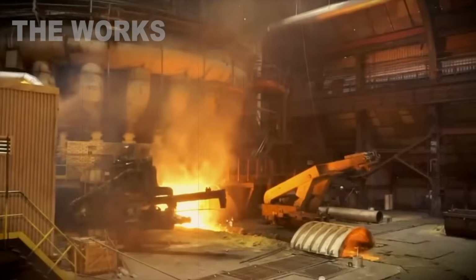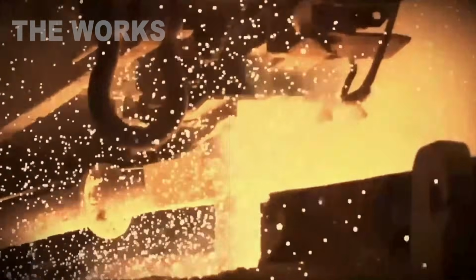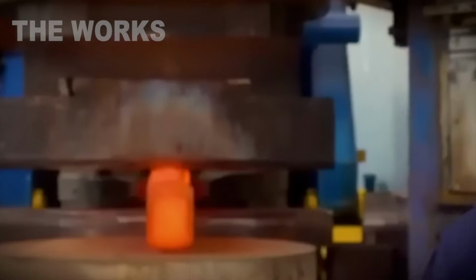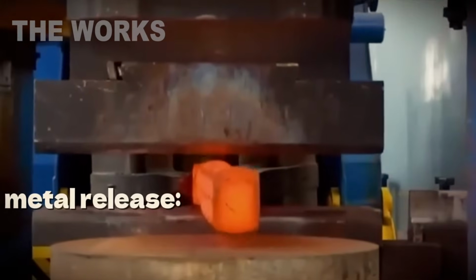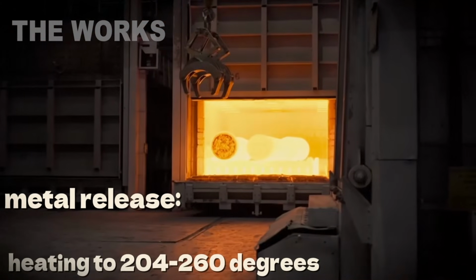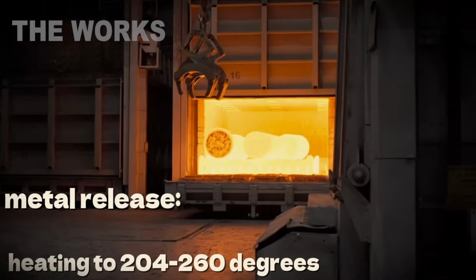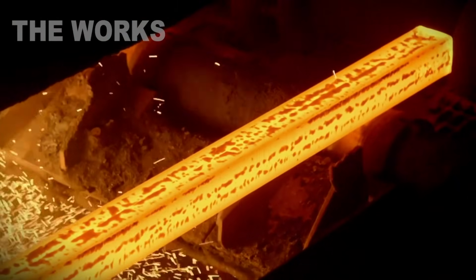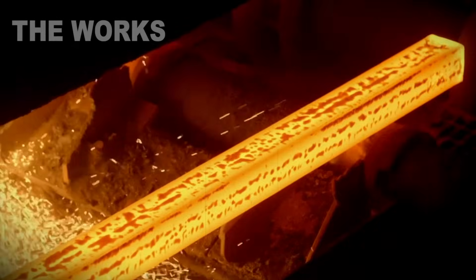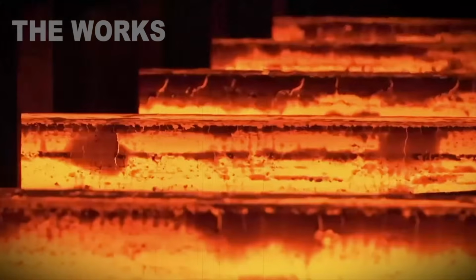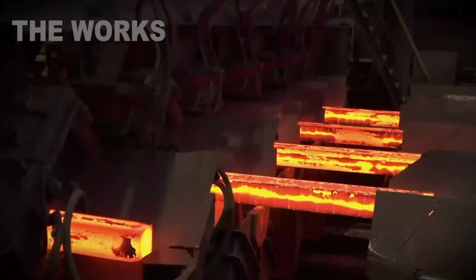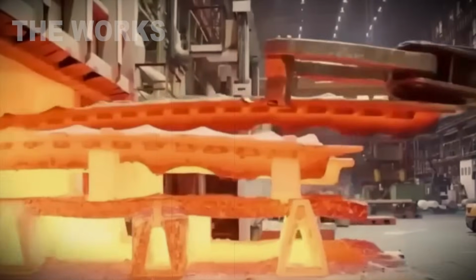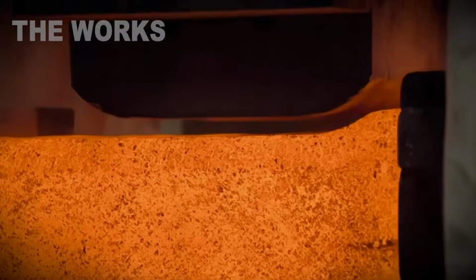But hardened steel is brittle as glass. One strike, crack. That's why there's a third stage, tempering. Heat to 400 to 500 degrees Fahrenheit. Hold for 4 hours. This relieves internal stresses, adds flexibility. Hardness drops to 48 to 52 units. Perfect balance. Hard enough not to wear down, flexible enough not to break.